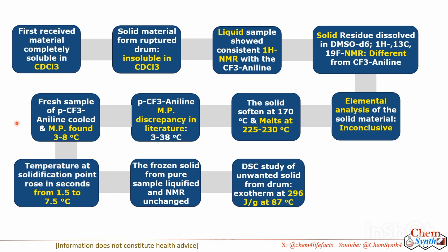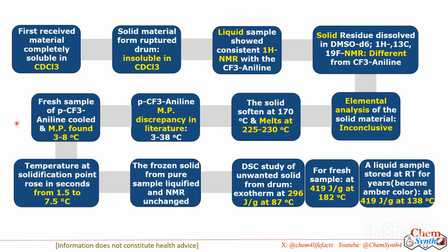Next, they performed some DSC study of that unwanted solid material from the drum, and they observed an exotherm of 296 joule per gram at 87 Celsius. And for the fresh aniline derivative molecule, they got an exotherm of 419 joule per gram at 182 degrees Celsius. They also had one liquid sample of that pure CF3 derivative of aniline. They stored it for more than a year at room temperature, and it became a little amber color. For that sample also, it was 419 joule per gram at 138 Celsius.